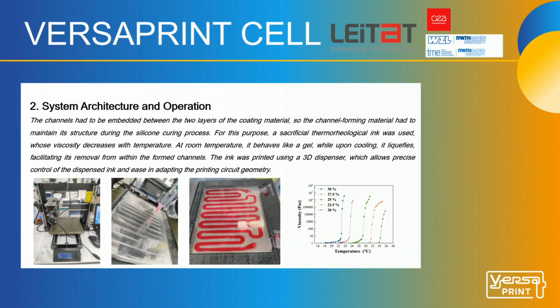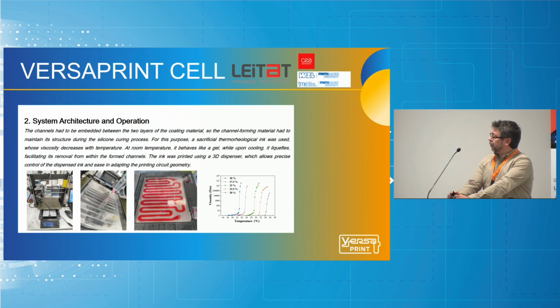So at room temperature, it behaves like a gel, but once cooled, it liquefies, and it's easy to remove from within the channels. This ink was printed using a homemade 3D dispenser, which allows precise control of the dispensed ink, and it's easy to adapt to different geometries and circuit sizes. Once we have this system with embedded channels and the silicone coating, we can empty the channels and mold the system for the VB1.